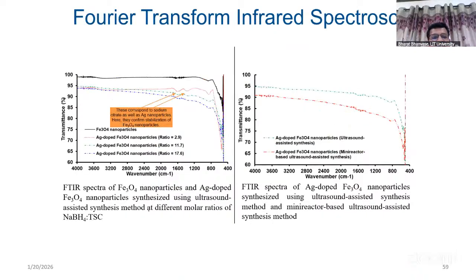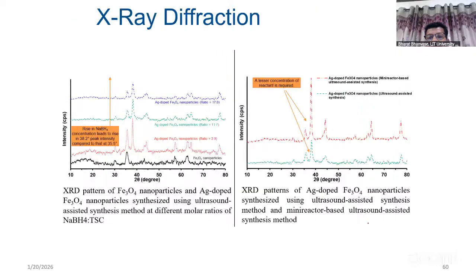FTIR also we have carried, we have seen different functional groups which are presented, prepared by ultrasound assisted method, microreactor system at different ratio. We have carried XRD analysis also. We can see this XRD analysis at different ratio, and the particular peaks which are present there will confirm the formation of Ag dope Fe3O4 nanoparticles. So that is with ultrasound as well as in microreactor.